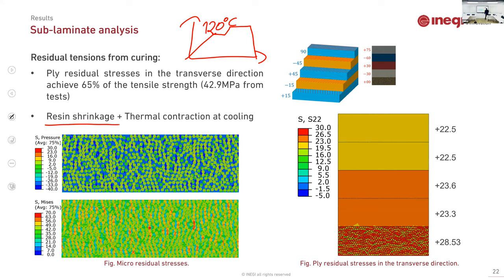If we go to the mesoscale level, since these laminates have different orientations, because of the orthotropy the laminates have different thermal expansion coefficients. And what is curious, let's say, it's also evident, each one of the layers has a residual stress, okay? Because one lamina wants to expand, and then after that wants to contract, but the adjacent layers do not allow that. So the complete layout needs to achieve an internal equilibrium, okay? And this internal equilibrium induces that, for example, in this internal layer that is modeled at the microscale level, almost 28 megapascals develop.